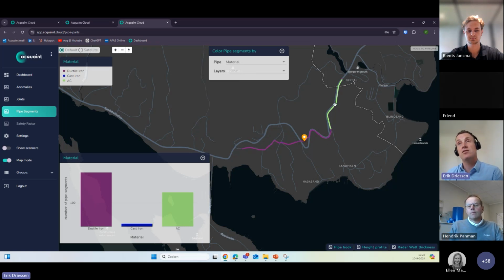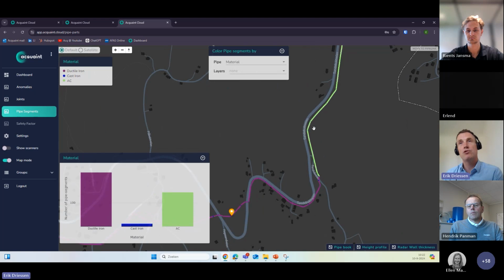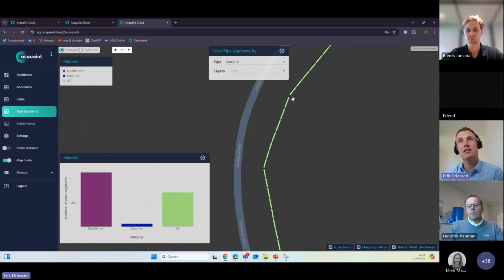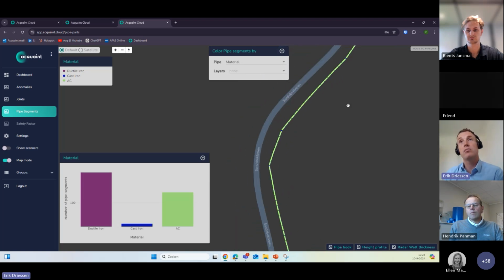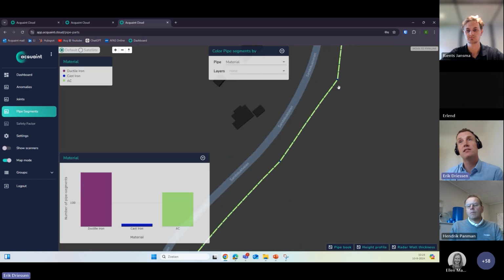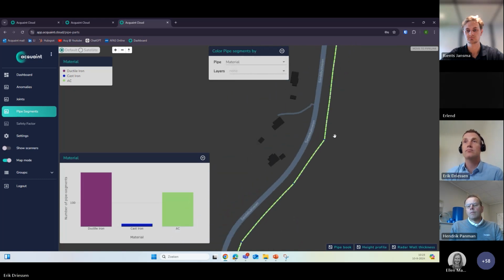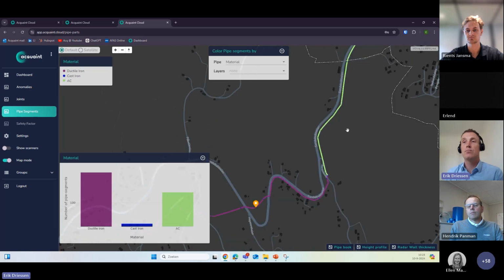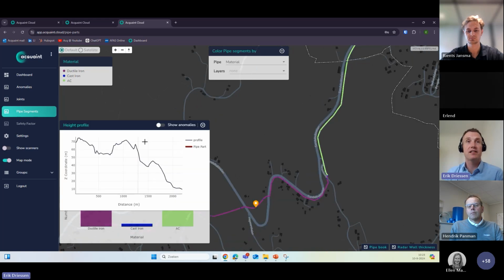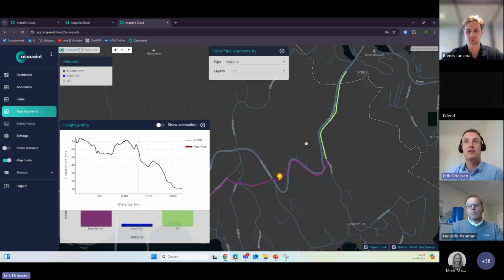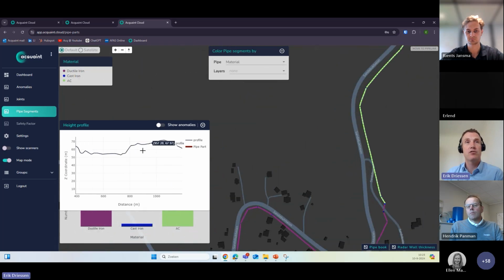And here you can recognize the asbestos cement part at the start, and then it goes over in ductile iron. And like Riens explained, mostly the bent pieces, like here, small blue part there, those are cast iron bent pieces, which are applied almost with every bend. There's one. So that's the material. Also here, by the way, you can select the height profile, and when you zoom out or zoom in, the height profile is adapting to the piece of the pipe that is in view.